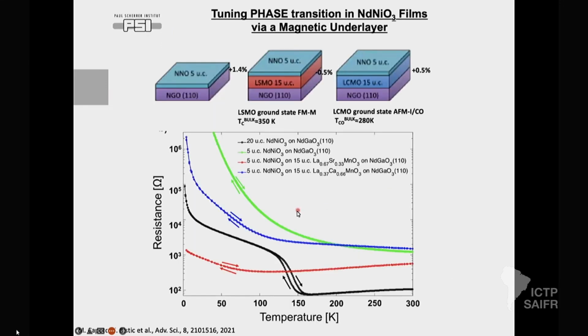For that, we actually use a magnetic buffer layer. We grow a nickelate film, which is now ultra thin, over the LSMO, which is ferromagnetic, or LCMO, which is antiferromagnetic. You could see in the transport there is a drastic change depending on what you put below. If the system is unbuffered, it's an insulator. If the system is on, for example, a ferromagnetic layer, it is almost metallic all the way.